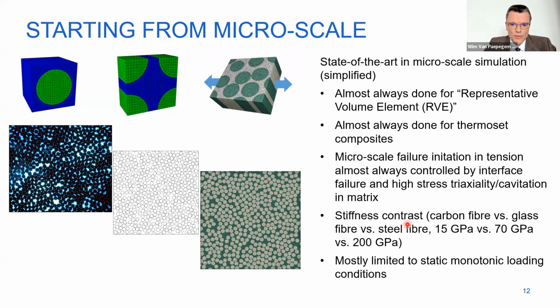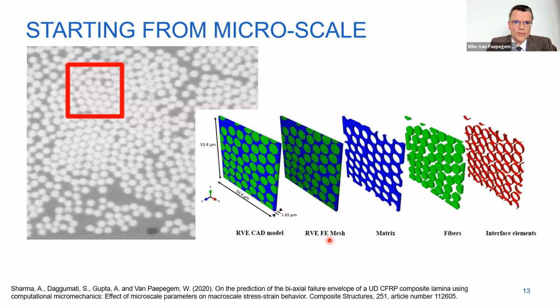And very important is also the stiffness contrast. So your fibers are like very stiff and hard inclusions, almost obstructions or obstacles in your polymer. So they create stress concentrations, and the relative stiffness difference between the fiber and the polymer is important. So here you see carbon, glass, and steel fiber. The stiffness mismatch with the polymer, which is typically a few gigapascal, can be very different. And mostly we simulate static monotonic loading conditions. So that's a bit our starting point.